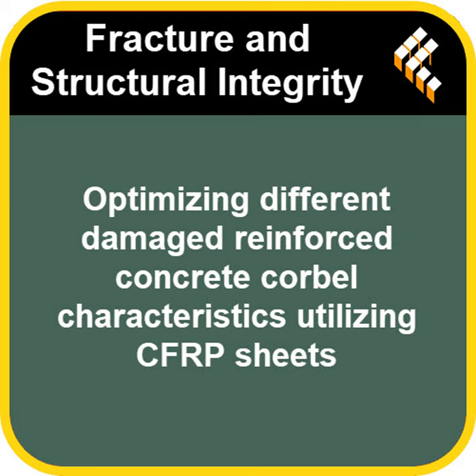Okay, makes sense. What's the second thing? The second thing is actually quite positive and maybe a bit counterintuitive. Even though failure initiated in the concrete, the way they failed was different. How so? The CFRP strengthened specimens showed more controlled, localized failures, and importantly, they exhibited enhanced ductility and energy dissipation. Wait a minute. Earlier you said CFRP is a brittle material. How does adding a brittle material make the whole thing more ductile? That sounds contradictory. That's an excellent question. It seems paradoxical, doesn't it?